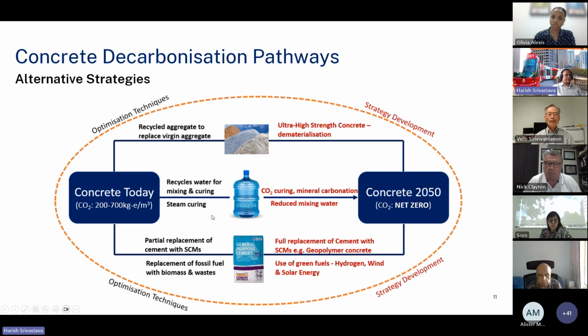At the moment, we use recycled water, steam curing, but probably we need to go to carbon cure type of technology where we inject carbon dioxide both while batching and also during the curing process. The advantage of this is, first, it locks the carbon dioxide into the concrete, so it is basically supporting carbon storage. And some of the papers have reported that up to 20% of strength improvement can be achieved by injecting the carbon dioxide. So that means it has got a dual benefit.